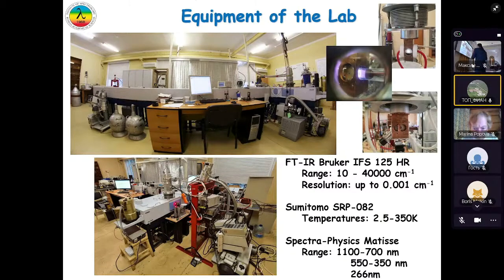0.001 wave number. We can also cool down our samples to 2.5 Kelvin using a closed-cycle helium vapor cryostat. We have several cryostats, but this is the last one, much more powerful than before. And for the excitation of the luminescence spectra, we can use a titanium sapphire laser with a doubler, as well as a number of diode lasers.